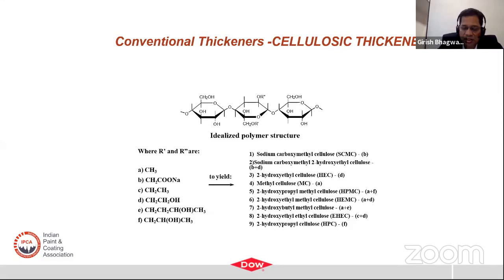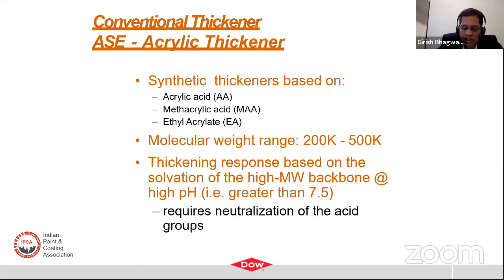And then, of course, long ago synthetic thickeners appeared on the scene when Rohm and Haas introduced alkali soluble emulsions. Basically, these are polymers of either acrylic acid or ethyl acrylate with 200,000 to 500,000 molecular weights. You neutralize this with an alkali, and then the chains open up and the hydrogen bonding, again, this is a conventional thickener. So the conventional thickening mechanism plays a role, right?